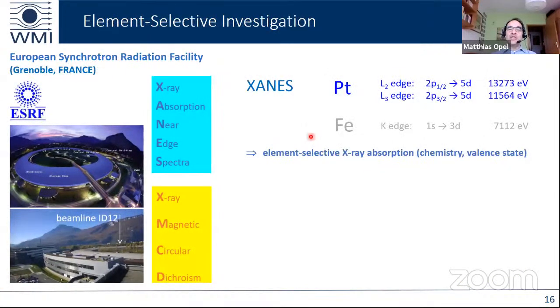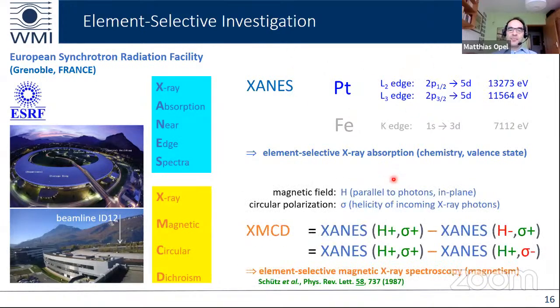The platinum edge, there are different platinum edges. The platinum L edges are at an energy of about 11 to 13 kilo electron volts, and for this you need hard X-rays, which can be provided by this synchrotron radiation facility. So we were interested in the X-ray absorption at the platinum edge. And then we applied a magnetic field to the samples. And then we also used the circular polarization of the incoming X-rays.